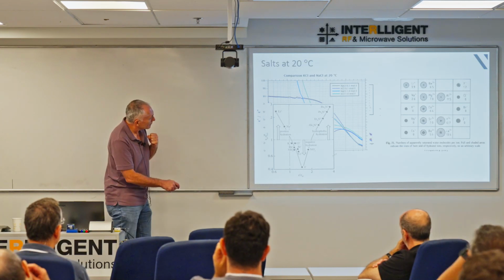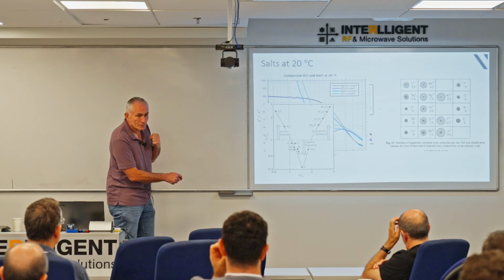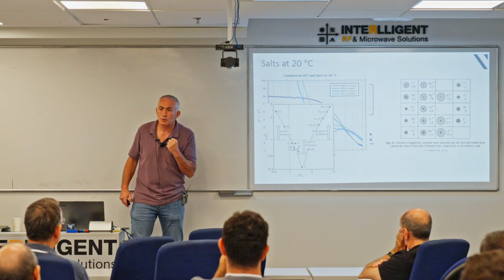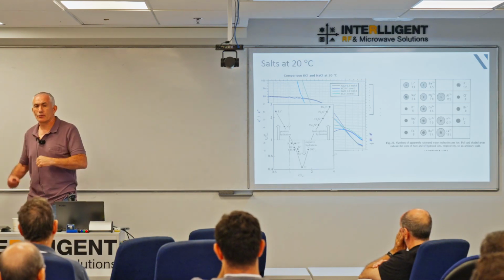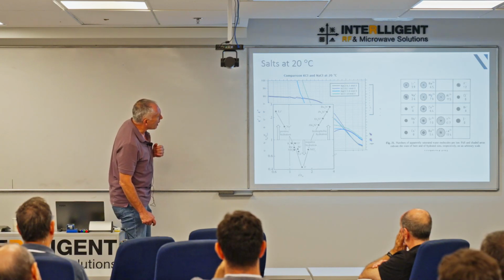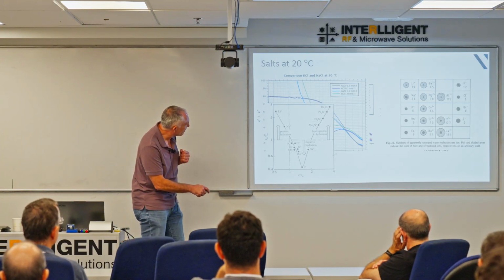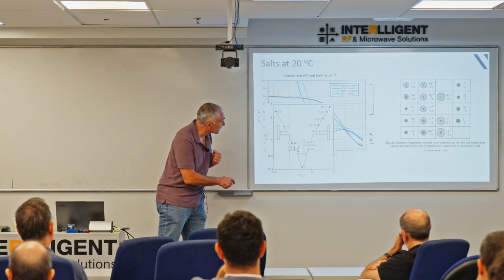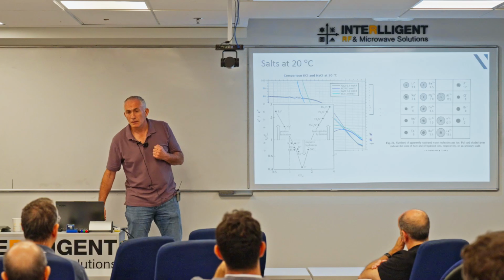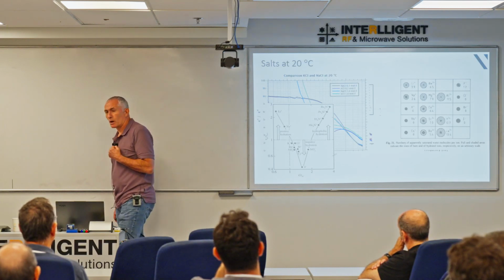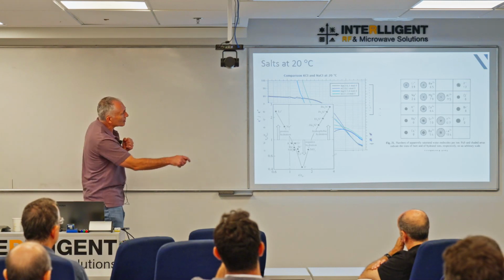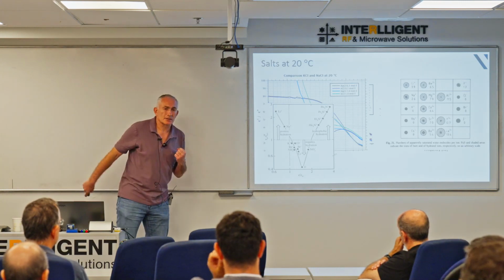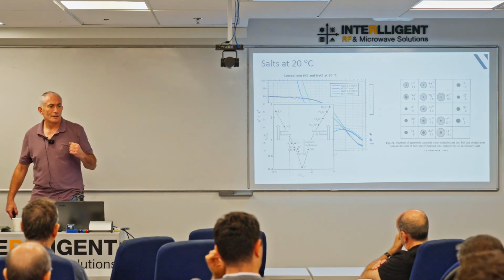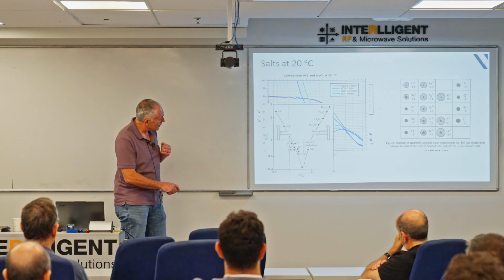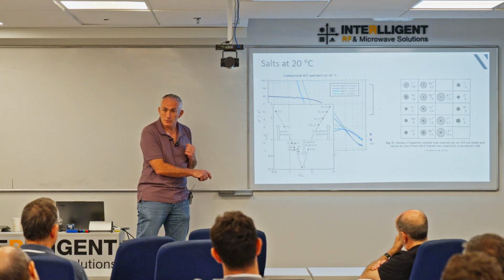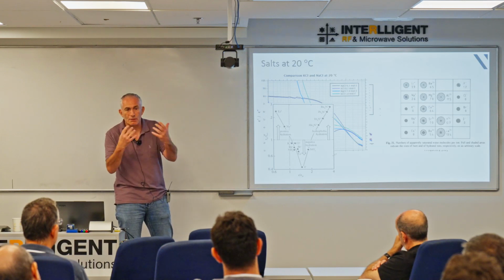Okay? Now, sodium is called positive hydration because it can hold a water molecule around it for about 20 picoseconds before the water molecule will break free. Where's magnesium? Lithium's even more. I don't have magnesium on this scale because it won't fit on this scale. Magnesium can hold a water molecule around it for about 1 microsecond, which means on this scale it is somewhere at the same height as the jets that land in Ben Gurion when they come over. Okay? Potassium, no. Chlorine, no. They will disturb water around them. They will simply throw it out.